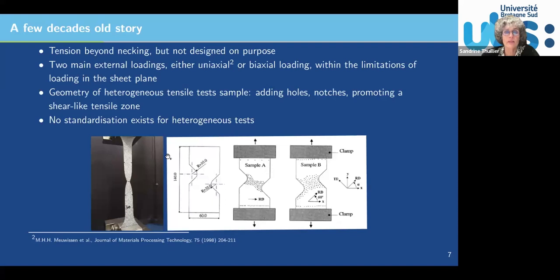So dealing with heterogeneous tests, it seems to be understood that one of the earliest ones is in 1998 by Mevisen, but maybe the very first one, and you recognize this is a tensile test, a very classical one, but beyond necking. And when you are beyond necking, this is obviously something which is non-homogeneous. But the problem with necking is that it's an uncontrolled mechanism. You never know exactly where necking will occur, so you don't control the heterogeneity, and it could be a little bit difficult to follow by digital image correlation.